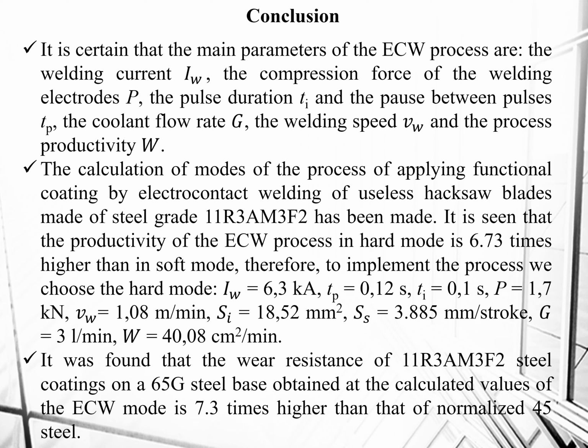It was found that the wear resistance of 11R3AM3F2 steel coatings on a 65G steel base obtained at the calculated values of the ECW mode is 7.3 times higher than that of normalized 45 steel.